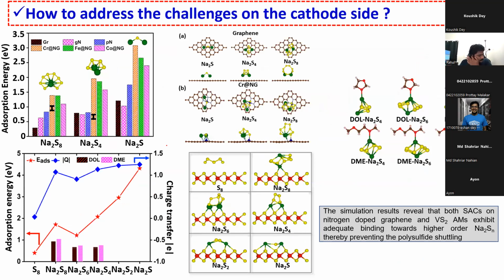Now, first we started with the single atom catalyst. So what is a single atom catalyst? As the name indicates, it is just a single atom, a transition metal atom. Why are we using a single atom? Because with a single atom, we have maximum utilization efficiency from this catalyst. If you have a bulk catalyst, something like a cluster, then the utilization of each atom towards the performance is very limited. That means not every atom will be involved in the catalysis. But if we have a single atom, that single atom will have the entire site to react, and the catalytic efficiency will be higher when compared to the bulk catalyst. So that's why we used a single atom catalyst.